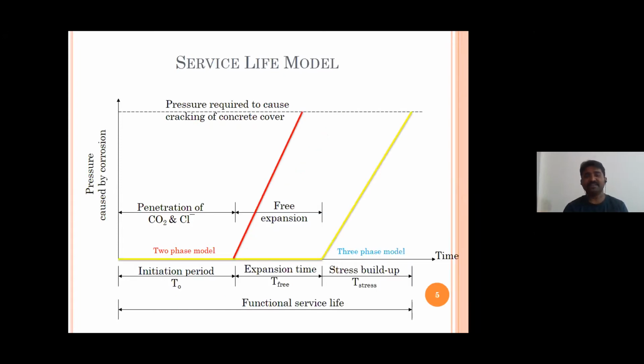After that, Liu and Weyers came up with the three-stage model. In this three-phase model, they have considered the effect of porous zone thickness. They believed that there is something happening at the steel-concrete interface that we need to identify, and they found out that there is a porous zone thickness. Until and unless that porous zone thickness is completely filled, there will not be any expansive pressure applied on the concrete. Because of that, they termed it free expansion or expansion time. So this is the initiation period.